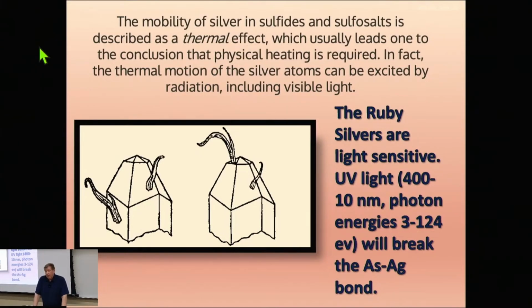And so if I look in a UV light, I'm going to break a bond. Now that bond that we break is related to the sulfur, but it's the bond that holds that little triangle together, and so we call it the silver arsenic bond. So if I take a nice piece of proustite and I take it to the bright sun, which has the appropriate UV signature to it, and expose that, I will eventually break the bonds. And if I do that, what I'll see is a white powder will begin to grow on the proustite. The proustite will begin to darken and it will grow silver on the outside. And so if I do this long enough, I get a black proustite crystal with a white powder, which is the arsenic recombining with oxygen from the atmosphere.